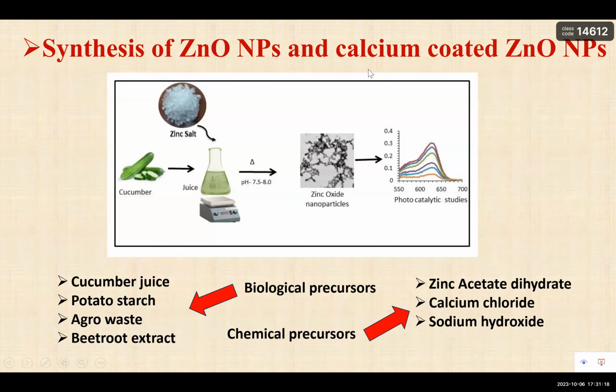The biological precursors we used in the synthesis of zinc oxide nanoparticles were cucumber juice, potato starch, agro waste such as orange peel, lemon peel, pumpkin seeds and peels, and beetroot extract. Whereas the chemical precursors used in the synthesis of zinc oxide nanoparticles were zinc acetate dihydrate, calcium chloride and sodium hydroxide. The procedure is very simple. We prepare the extract, mix the zinc salt in the extract, maintain a pH, and stir it for sometimes 4 hours, 5 hours, or relatively longer or shorter depending upon the reaction conditions. You see a color change, a visual change, and then the synthesis of zinc oxide nanoparticles is done.